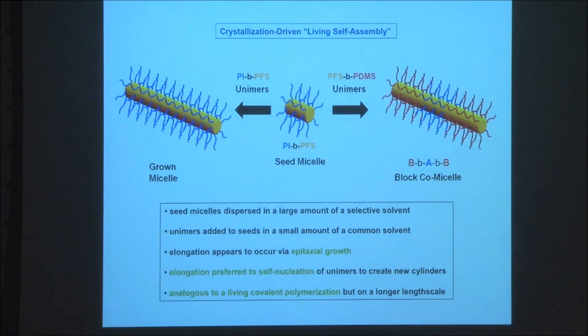And even more interestingly, if you do the same thing with a different corona-forming block, you will again deposit on the ends and grow the cylinder. In this case, you generate a segmented structure where you have different coronal chemistry along the structure. This is really a micelle analog of a block copolymer, so we call it a block co-micelle, where you have polydimethylsiloxane here in red from the added unimer at the ends, and the original seed is in the middle.